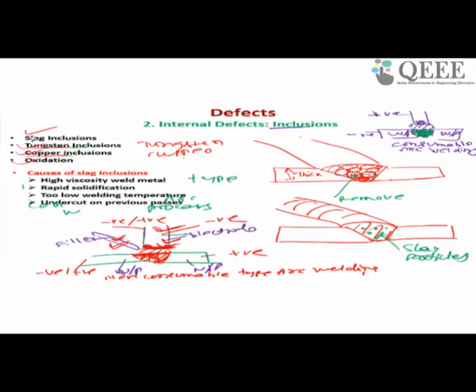For example, why do we get slag inclusion? What is the purpose of slag? The purpose of the flux is that it will react with the oxygen inside the material and form an oxide layer, in the form of slag. Since the slag is of low viscosity and lighter weight, it will float on the top, and you can easily machine it out to remove the flux slag. If the viscosity of your molten metal is very high, it will not allow the slag to come up. So you will get slag inside the material. This is because of the high viscosity of your metal.